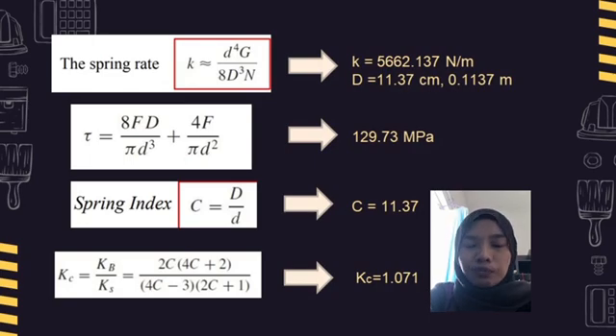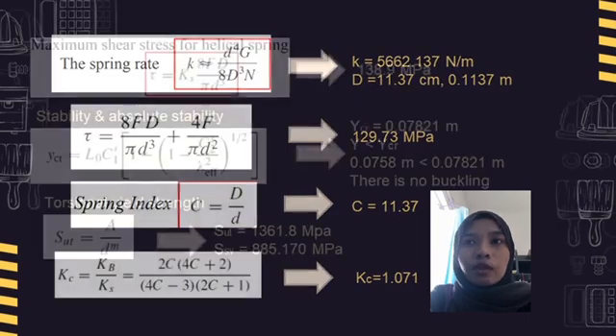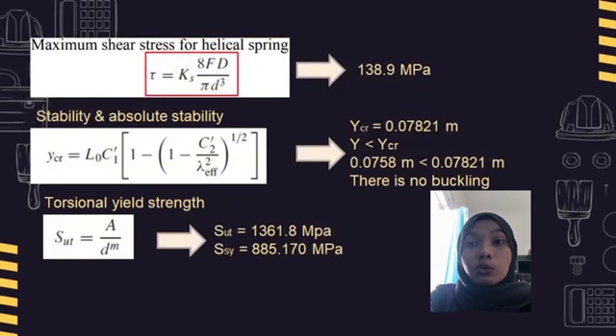There's no need for the curvature effect, the stress concentrated type of effects on the inner fiber due to curvature, so it can be ignored for static ductile condition due to localized cold working. For the maximum shear stress for helical spring, we use this formula. From this formula, we get a value of 138.9 megapascal.